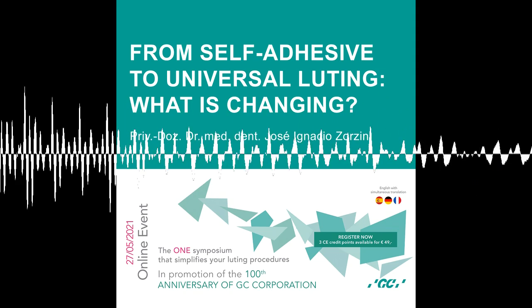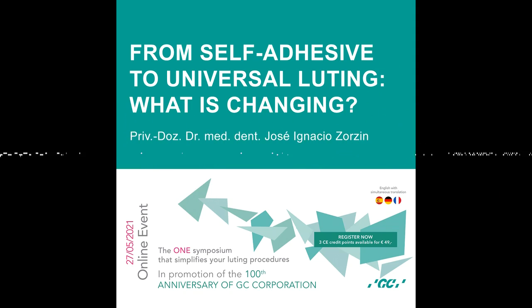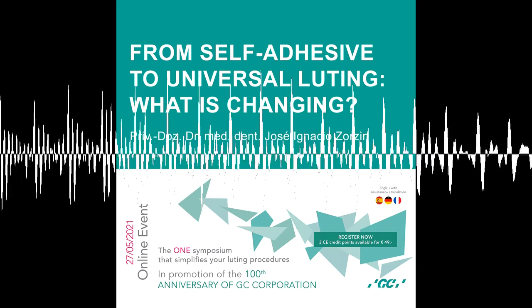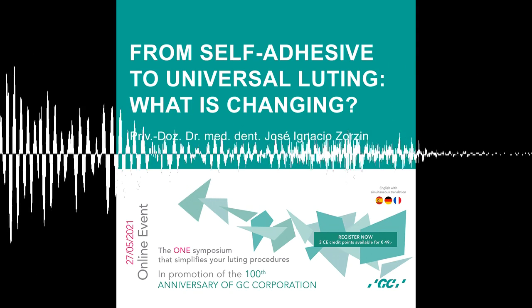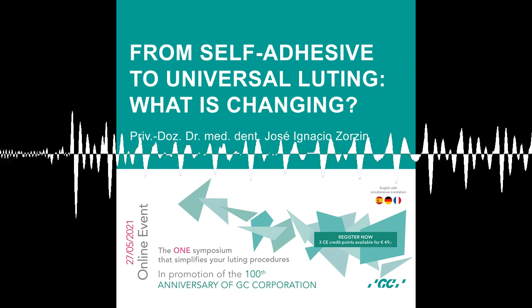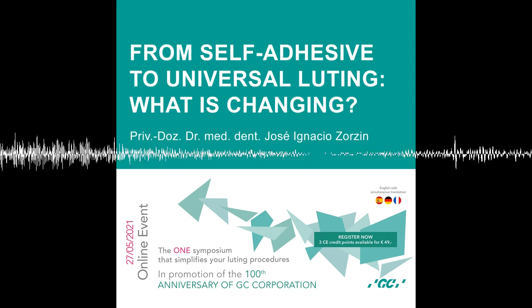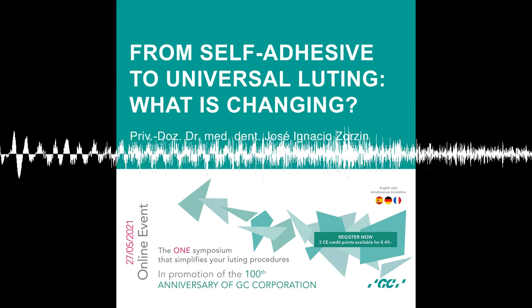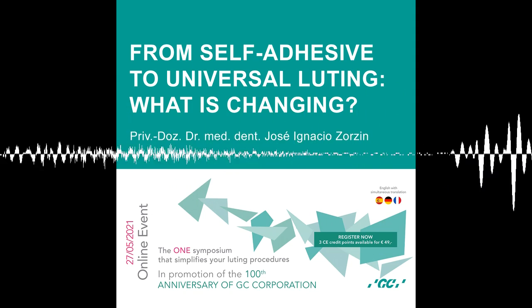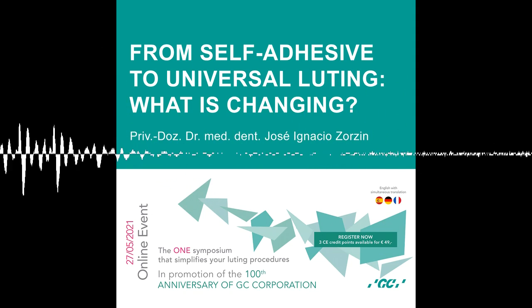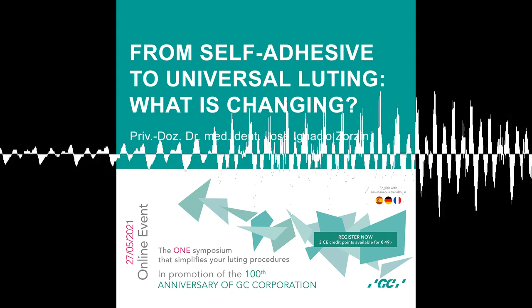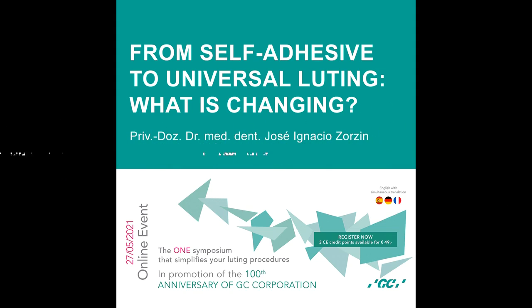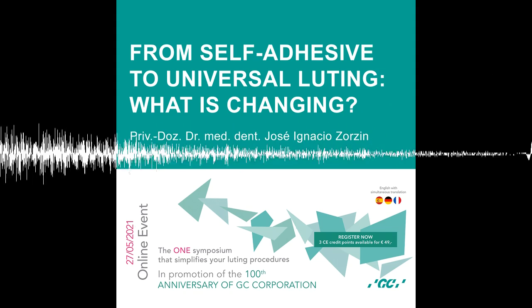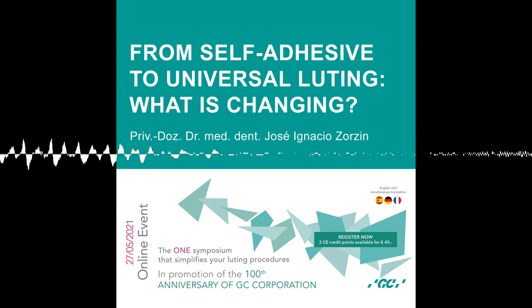Maybe it comes from the time when you etched your glass ceramic, then you placed the silane on it, and then you put unfilled resin on the surface. After putting this unfilled resin on the silanized surface, you had to protect it from light because this was light curing. Probably it comes from this, but a mere silanized ceramic surface with the normal products we use nowadays doesn't have to be protected from light. Maybe it's just a good place so the inlay is not getting lost. It's a safe place, so it won't fall down.